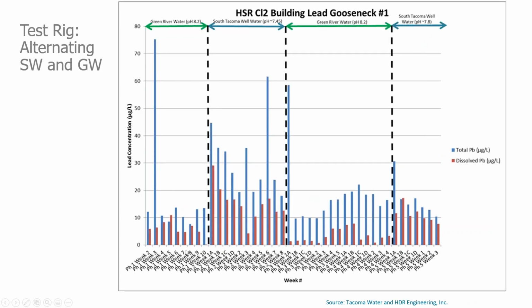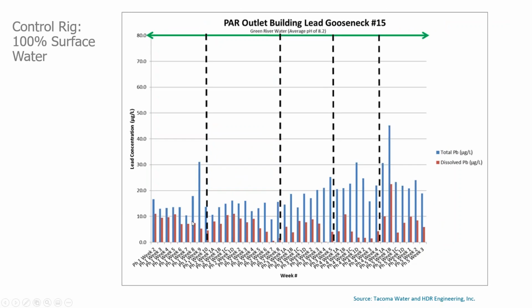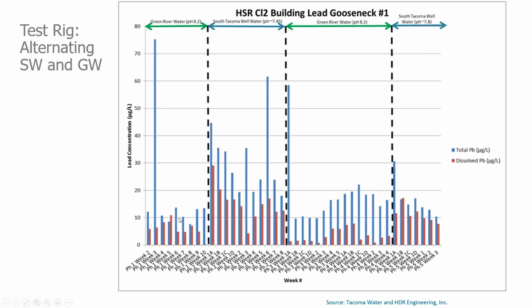Now this is the test rig where we were alternating between surface water and groundwater at the chlorine building on one of the goosenecks, the remaining gooseneck, the one that stayed through the whole procedure. And interesting to note, in the first phase with all surface water, we had very similar results, around 10 dissolved, between the control gooseneck at a different location and our test gooseneck at this location. So that was a good sign.